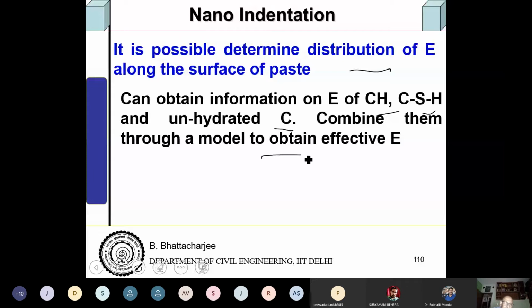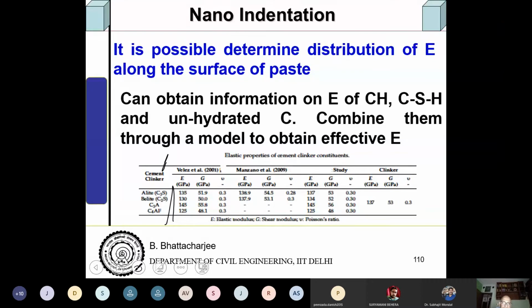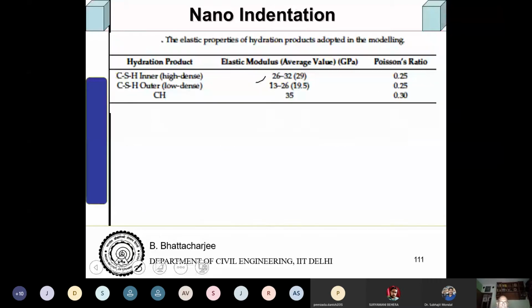For example, if you see the elastic properties of cement clinker, the various compounds, you find the elastic modulus is something like 135 GPa, etc. So average clinker would give you 137 GPa. Steel is 200 gigapascal. Average clinker, or unhydrated cement particle, is 137. Let's see the hydration product. CSH gel, the inner product after hydration, is 26 to 33 with average 29. And the one which goes outside the boundary is only 19.5. And calcium hydroxide is 35. So you can see that this is much less. Therefore, unhydrated cement is stronger.